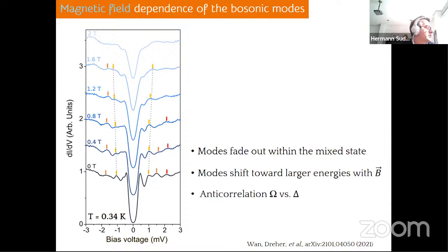And now the thing which really puzzles me is that with the 2 Tesla curve, how is the density of states of the normal phase? You certainly know about the ideas of Altshuler-Aronov and all these localization effects. So you could very easily make a sort of phenomenon, thinking like in universal conductance fluctuations, which gives you features in the density of states which are related not only to the superconductivity, but also to the normal phase. So how can you exclude this?